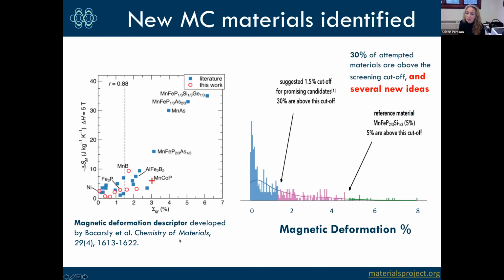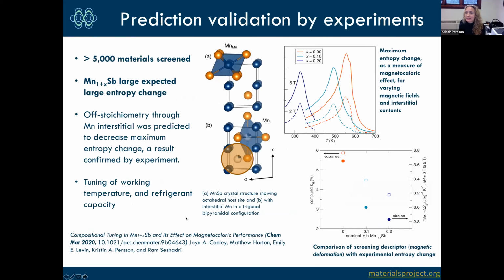So we did that. We calculated this magnetic deformation parameter. And as you can see, most of your materials fall in the not so great performing bucket around basically zero magnetic deformation. But there is a tail, and that tells you that there is some promise out there. There are materials outside of the known ones that have a potential predicted high magnetic deformation. So we're looking up here in the 6 to 8% range. One of these materials was a Manganese Antimonide, and this is a material that is known. It's known how to make it, but it had never been identified as a Magneto-Caloric material before. So that was new. But the good news is there was a synthesis recipe for this material.